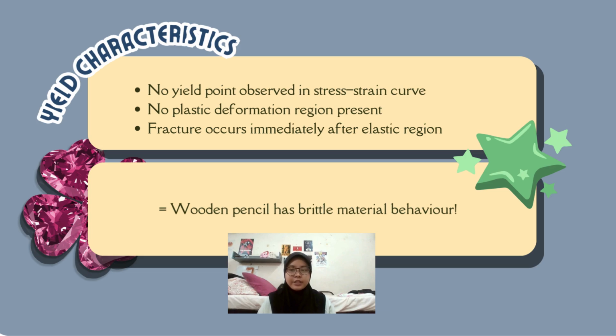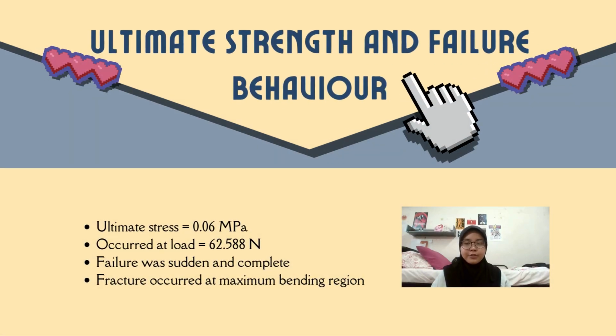The pencil fractured immediately after the elastic region without showing any permanent deformation. This confirms that the material behaves as a brittle material rather than a ductile one. At the maximum load of 62.588 newtons, the stress reached 0.06 megapascal and the pencil fractured suddenly. This indicates the ultimate strength and failure point of the material. The fracture occurred at the region of maximum bending, which is typical for wood under flexural loading.